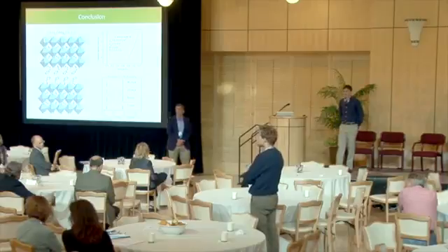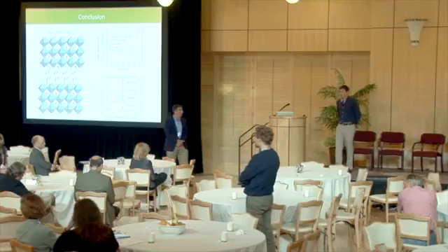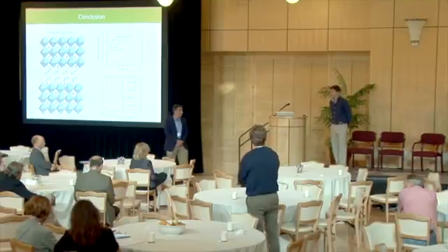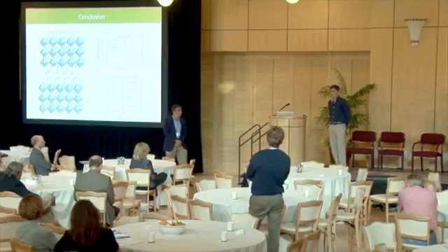Cool. How much does the series resistance increase from the bulk to your layered 3-layer structure? The 3D perovskite, are you talking about the 3D perovskites? Yeah. Those devices, most people can make them such that the series resistance is pretty small. I don't make those devices. I don't think I've ever made a complete device out of that material. Does your cross-plane connectivity decrease because you're basically cutting off the conduction pathways? Yeah, we do think we are limiting the current or the mobility in that direction specifically. I did collect an EQE spectrum and an IQE, and we do know that we're not getting all the carriers out that we generate, and we think that's probably because of the limited carrier mobility. So yeah, I think it's likely coming from that.